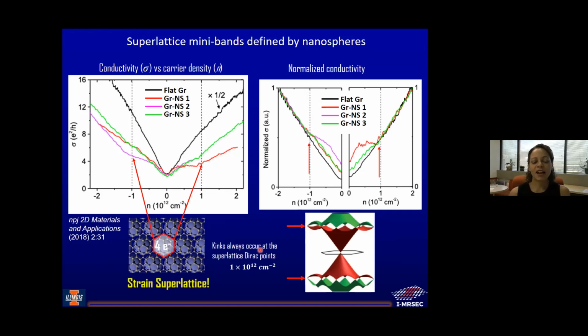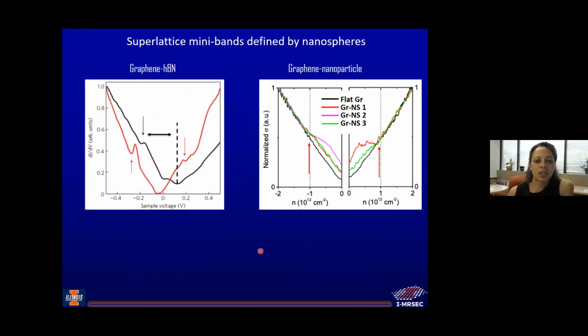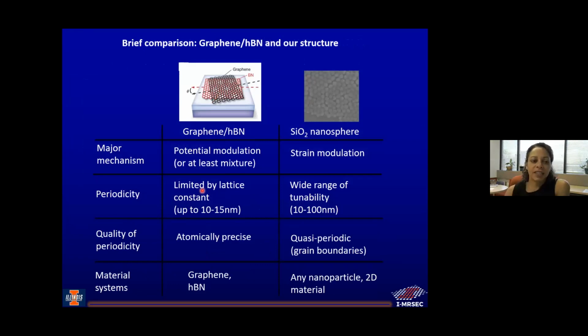Okay, so what we have here is a strain superlattice. Okay. Well, how do we know? And just to point out, you can see again, this is for graphene HBN, and this is for our devices, the nanoparticles, and you can see very similar sort of behavior. You can compare the graphene HBN to what we have, and they're limited by this lattice constant. We have a wide range of tunability. Even though the graphene HBN is atomically precise, we do have some quasi-periodicity that allows us to see the effects, and it can be useful for any sort of material structure.